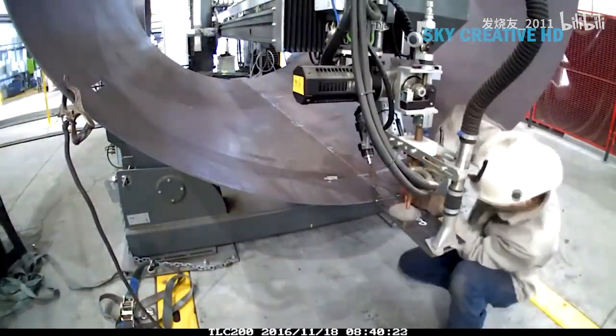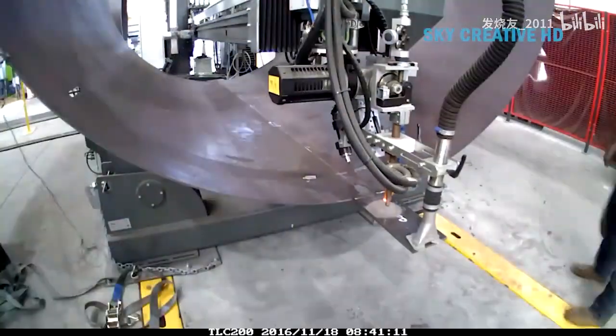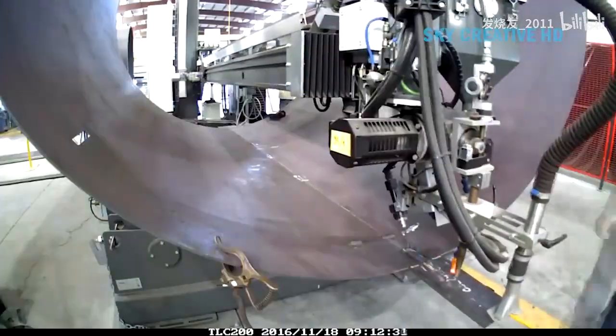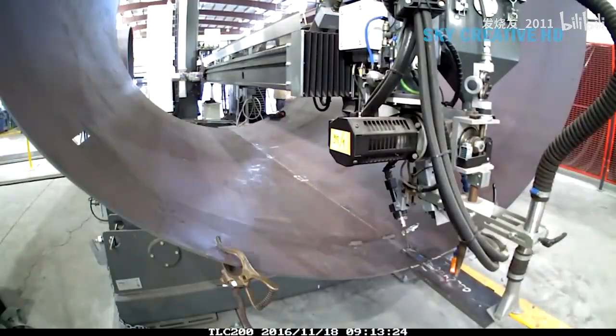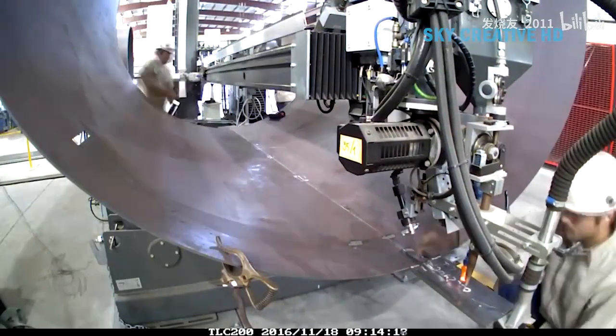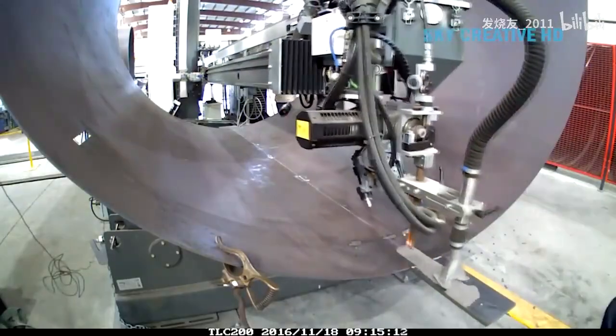Tank shells usually need to be cylindrical. This means the flat plates must be rolled into curves. Using a 3-roller plate rolling machine similar to the one seen before, the edges of these rolled sections are then prepared for welding. Usually, bevel cutting is used to allow the weld to fully penetrate the material thickness.